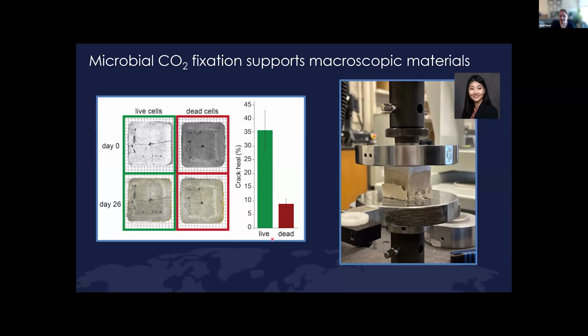What this also means is that you now have a building material that can basically do direct air capture. The way these microbes do self-healing cement is by taking CO2 from the atmosphere and attaching it to a calcium or magnesium ion to basically make limestone. And we can show that just having our coated live cells in this dry mix enables significant crack healing. These are about 0.5 centimeter wide cracks, and we get about 40% of that crack filled in. Because we get very little background filling with those dead cells, this tells us that having these cells alive and happy in this matrix is critical for the success of this. I also want to note that these are 10 centimeter by 10 centimeter cement pucks, so these are fairly large cracks that have formed, and we see visible changes in healing.